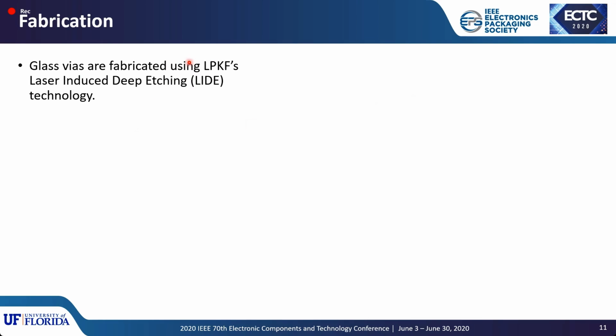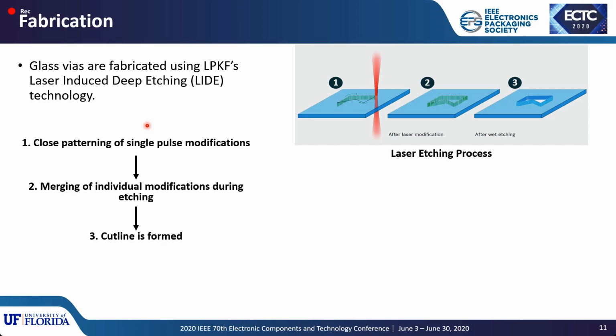Firstly, the glass vias are fabricated using LPKF's laser-induced deep etching technology, where in this process you have three main steps. First, you use single pulse modifications to closely pattern the vias on the glass substrate, and you try to merge these individual modifications together and etch the glass. And finally, after the wet etching, you can clearly see the formed pattern on the glass substrate.